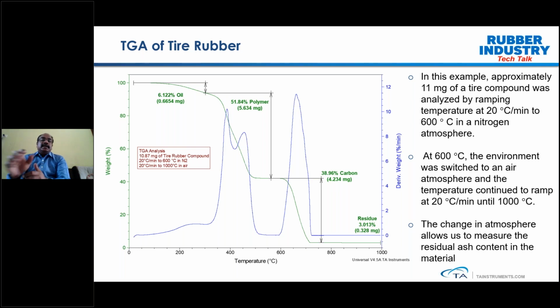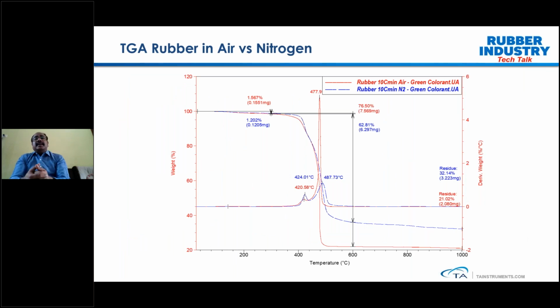And what is so peculiar here is that as you see the polymer decomposition, the derivatives show a kind of shoulder, which signifies that it is not a single polymer decomposition; it may be a multiple composition. On many occasions, since we are using a multi-component system and a mix of polymer blend, standard TGA would be a challenging aspect.